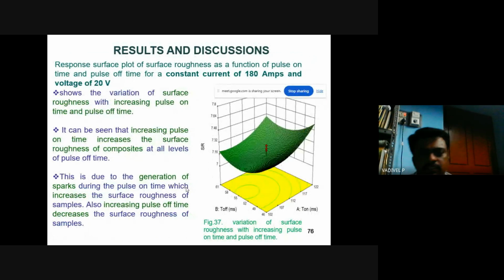The next plot is the variation of the surface roughness with increasing pulse on time and pulse off time, at a constant 180 amps and 20 volts. Increasing the pulse on time increases the surface roughness at all levels of pulse off time. This is due to the generation of spark during the pulse on time, which increases the surface roughness of the samples. Also, increasing the pulse off time decreases the surface roughness. The previous slides showed a similar graph for surface finish, and this one is for surface roughness of the samples.